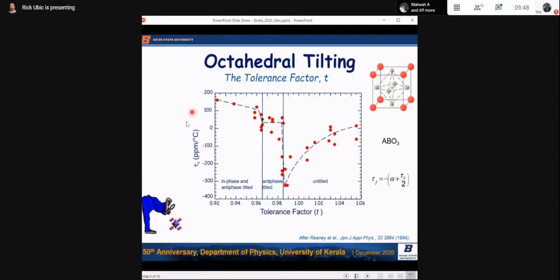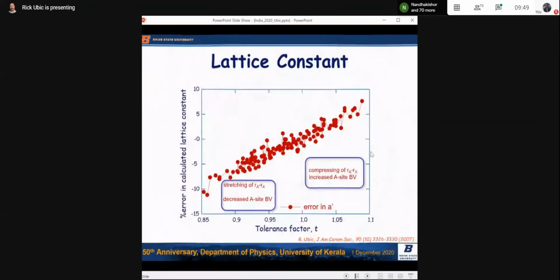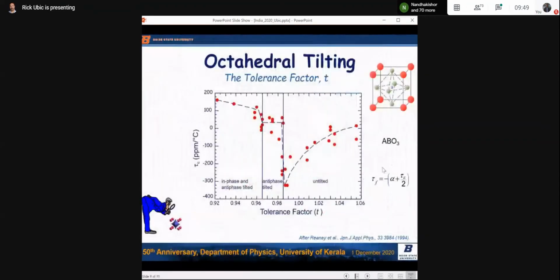So, okay, this is the temperature coefficient of permittivity. This basically tells you how much the permittivity, or the dielectric constant, changes with temperature. For most devices, you want that not to change, or not to change very much, right? And the sort of mirror parameter, tau f, oh my goodness, it's not behaving for me. Here we go. There we go.